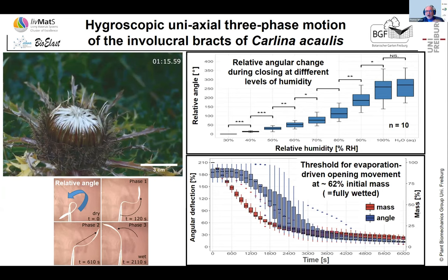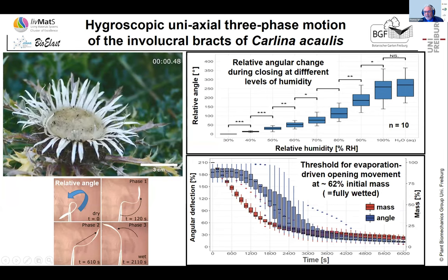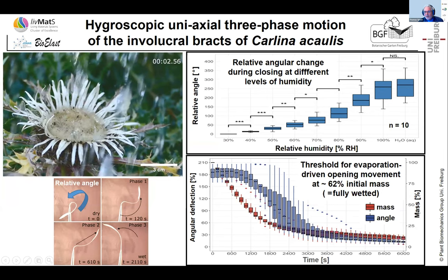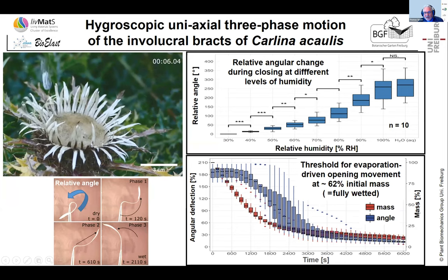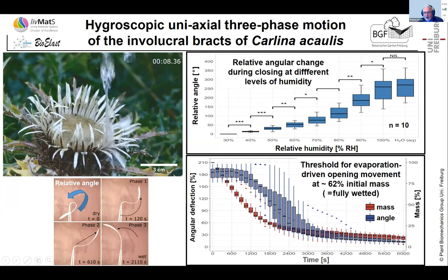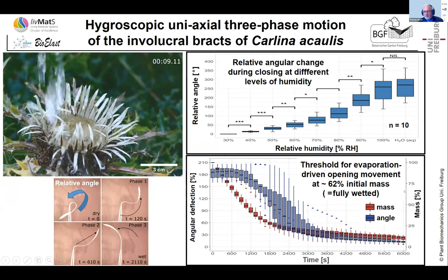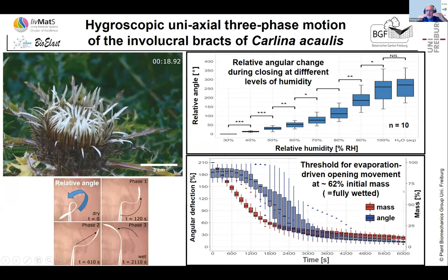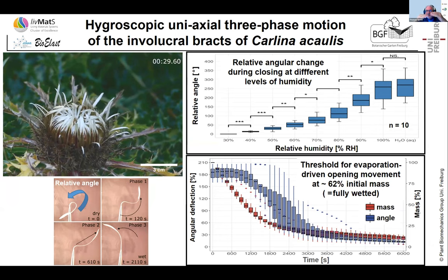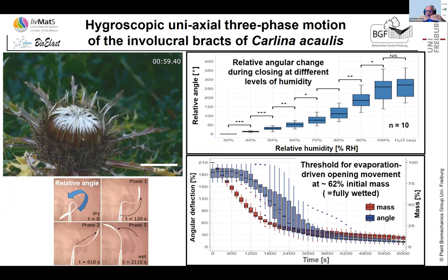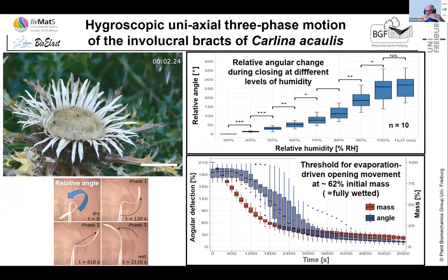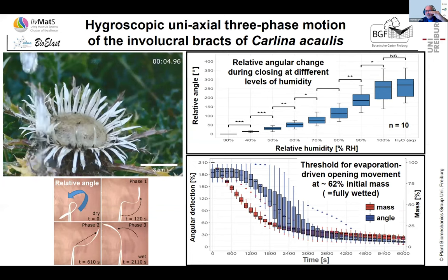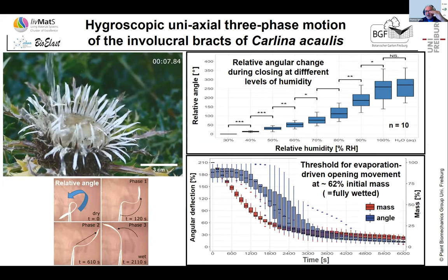phase before it starts. This is the angle in blue, and this is the mass. And the mass is a measure for the drying out. And you see that the motion doesn't start before the mass has gone down to about 62%. So you have a kind of period where nothing happens. So up to 35, 38% of the humidity can evaporate before the motion starts. And this is very important for technical application, because if you had a system which reacts to changes of 1% humidity, you would always have this wiggling, which you don't want.